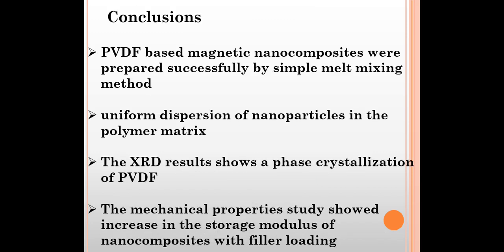So in conclusion, PVDF based nanocomposites were prepared by a simple melt mixing technique. The uniform dispersion of Fe3O4 nanoparticle is observed in our nanocomposites. The XRD study indicated alpha phase crystallization of PVDF. Mechanical properties showed an increase in the storage modulus and also the presence of rigid amorphous phase.